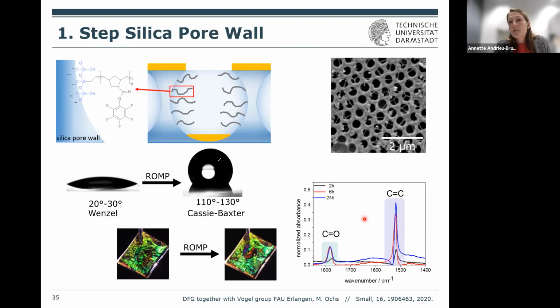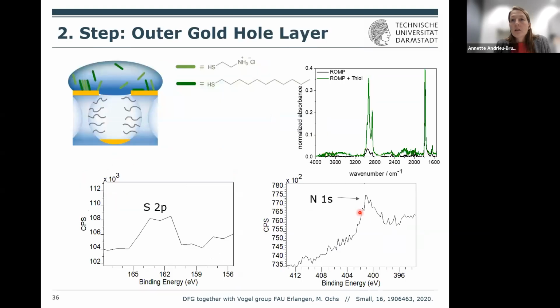And as well, infrared spectroscopy shows you that there is polymer in these pores. So the second step then was to discriminate the outer gold layer from the bottom gold layer. And this we did by using water as a solvent on a very hydrophobic pore. So the aim was to just functionalize the outer surface of the gold by using thiols, thiol deposition from water.